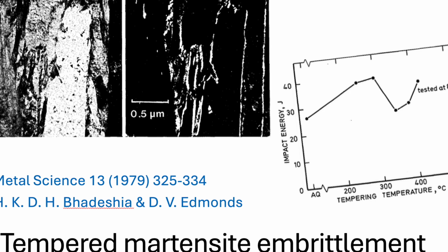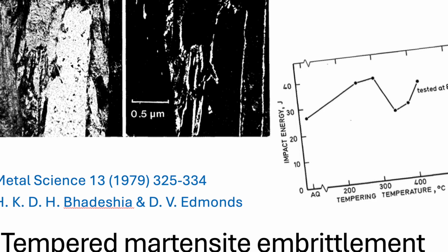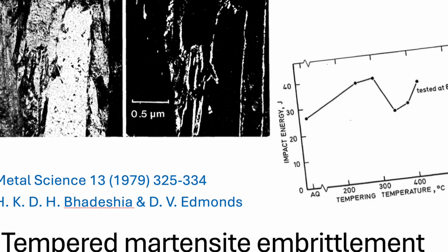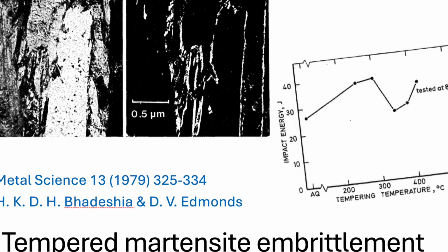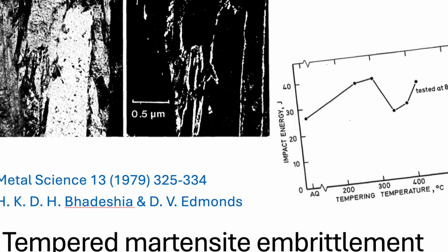And to study TME, the researchers focused on one specific candidate alloy, an iron-carbon-molybdenum steel, specifically Fe-4Mo-0.2C. Why that one? This molybdenum alloy is crucial because after the initial quench, it retains a measurable amount of something called residual austenite, about 5%. Residual or retained austenite. Okay, so that's our first main character here. Definitely. And what exactly is retained austenite? Is it just leftover stuff? Pretty much. It's the original high-temperature phase, austenite, that should have transformed into martensite during the rapid cooling of the quench. But it didn't quite finish. So it often sits there as very thin, often unstable films right between those martensite laths we just talked about. So it's stuck between the needles. Stuck between the needles, exactly. And previous research had already hinted that TME in this specific system might be fundamentally tied to what happens to this small amount of unstable retained austenite.